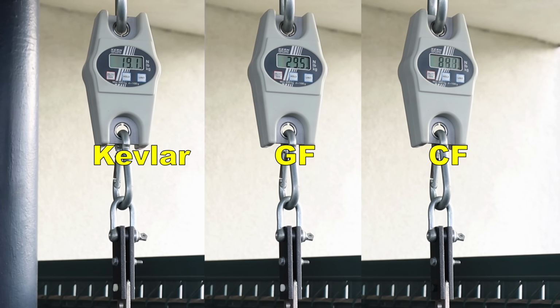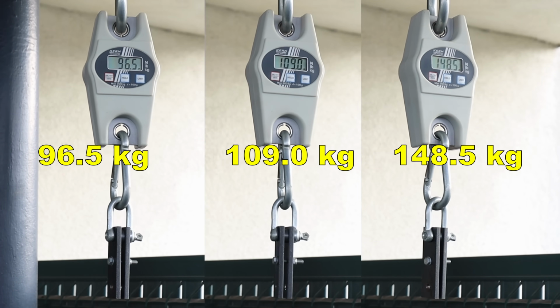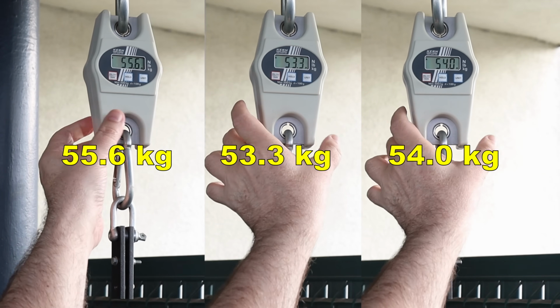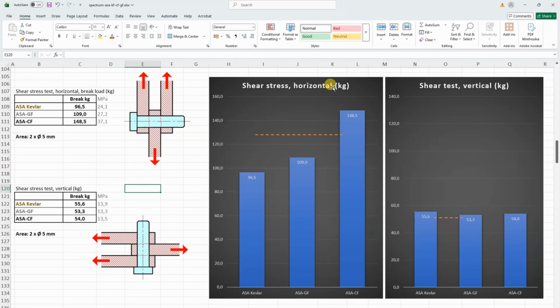Shear test, objects printed in horizontal position, side by side all three materials, and these are printed in vertical position. Here the layer adhesion is important. When printed in horizontal position, the fibers always help a lot, but only the carbon fiber version is stronger compared to the average ASA without any fibers. The Kevlar and glass fibers are below this line. Printed in vertical position, the layer adhesion is important here, but interestingly in all three cases, these are very similar numbers, and more or less quite weak compared to other filament types.